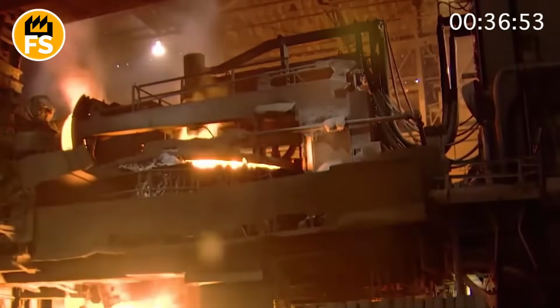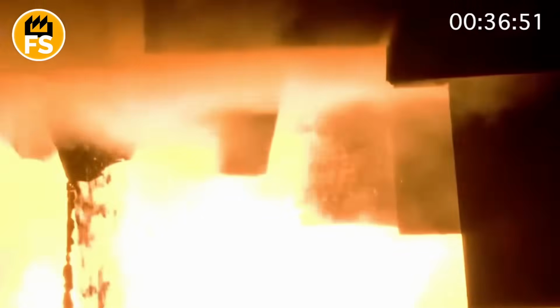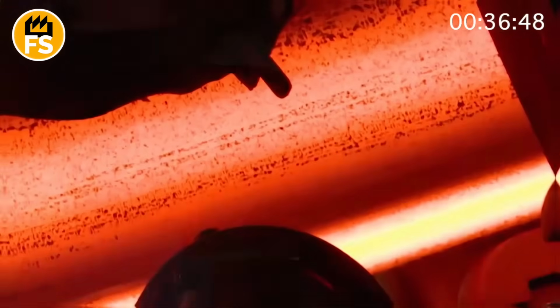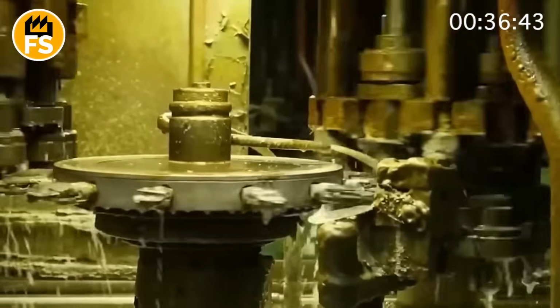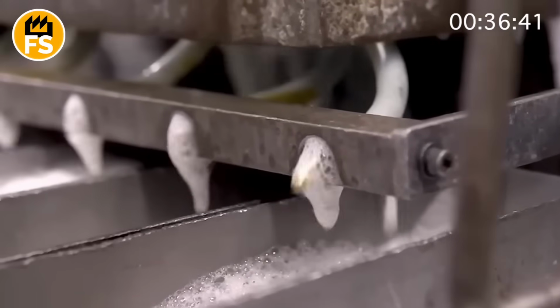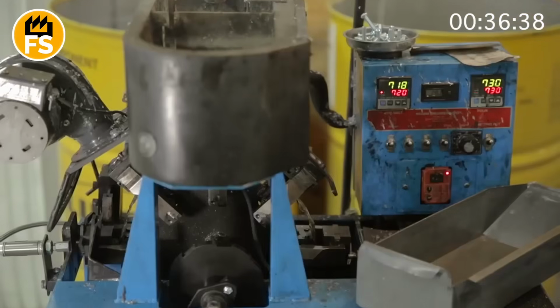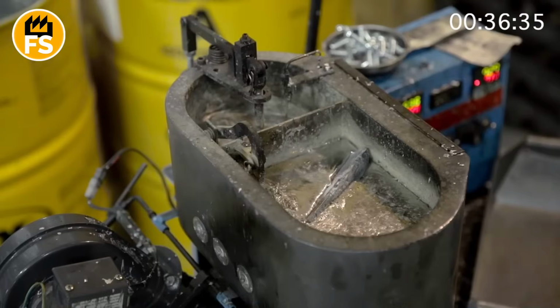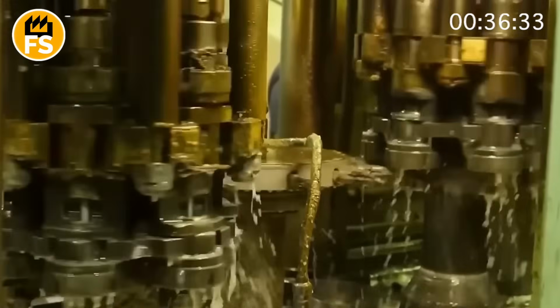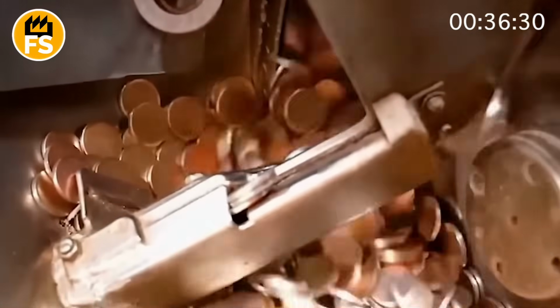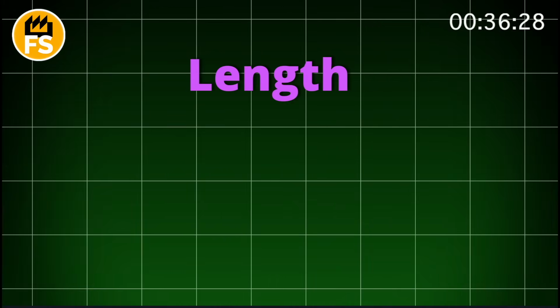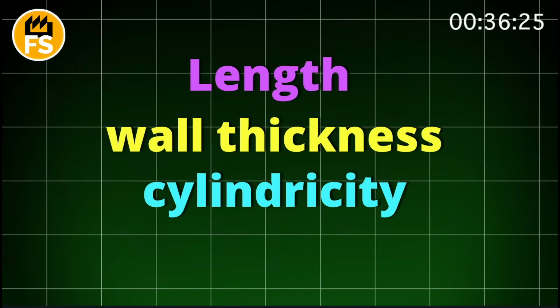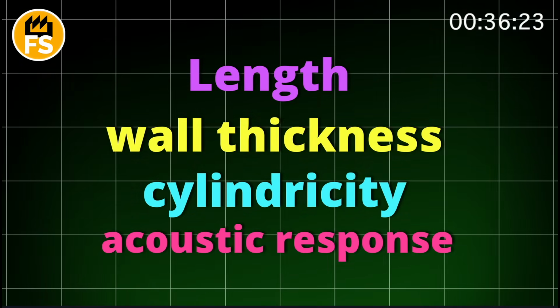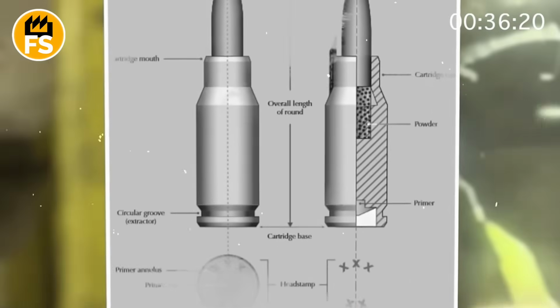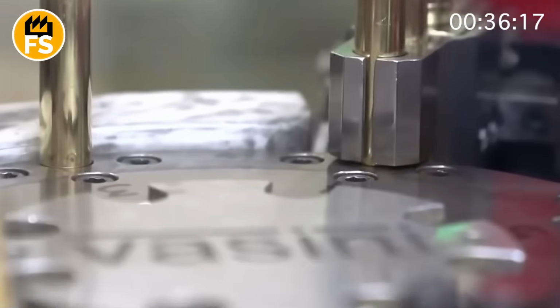Each casing is annealed after drawing. This involves heating it to 1,000 degrees Fahrenheit to relieve internal stress in the metal. Otherwise, the casing could crack during firing. Then, it's cooled in water and cleaned in an acid solution to remove scale and lubricant. Next, calibration and weighing. The casings pass through a high-precision laser control system. A weight discrepancy means automatic rejection. Length, wall thickness, cylindricity, and even acoustic response are similarly checked. Special sensors detect if a casing has microcracks or internal defects.